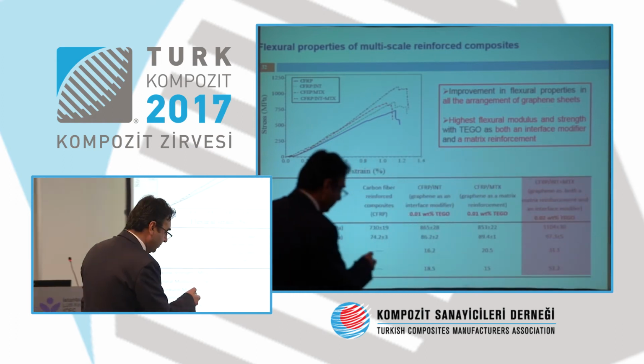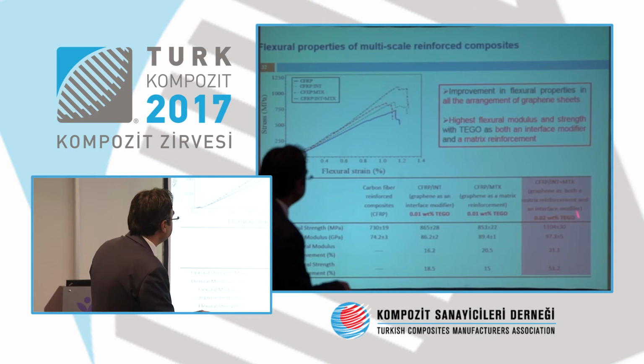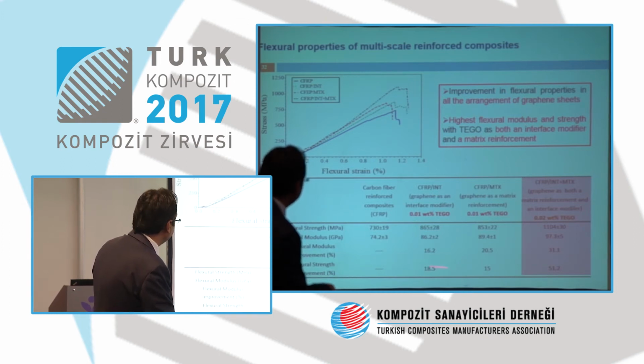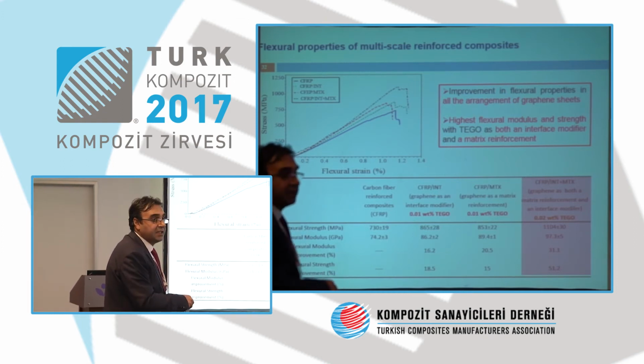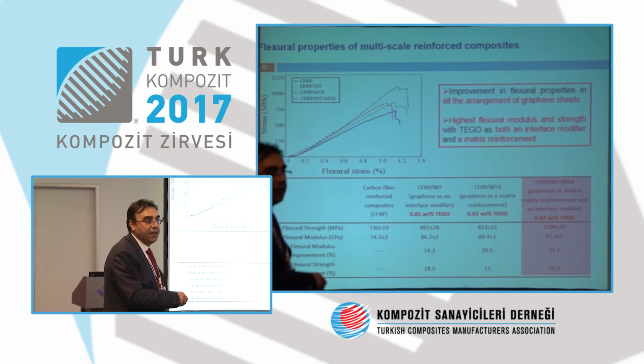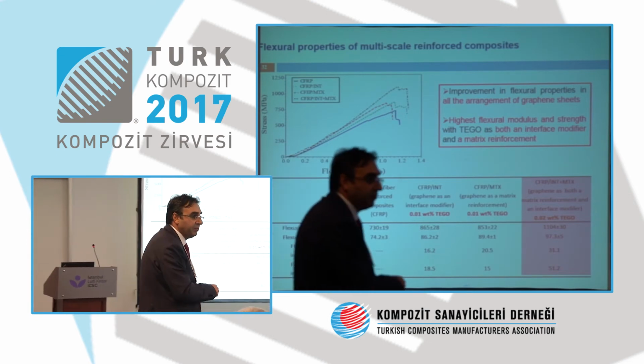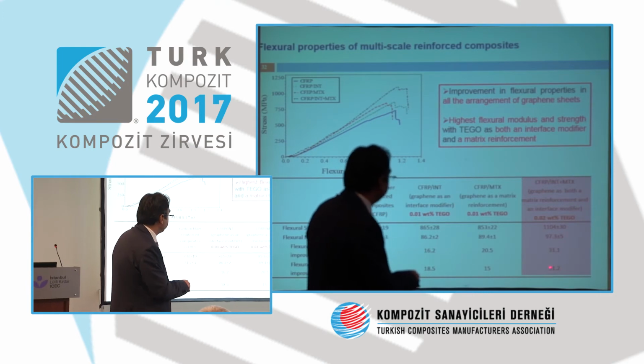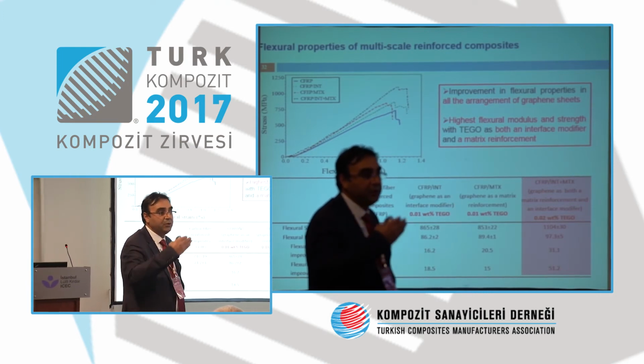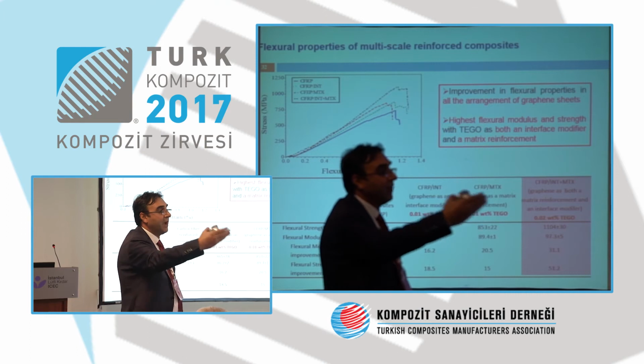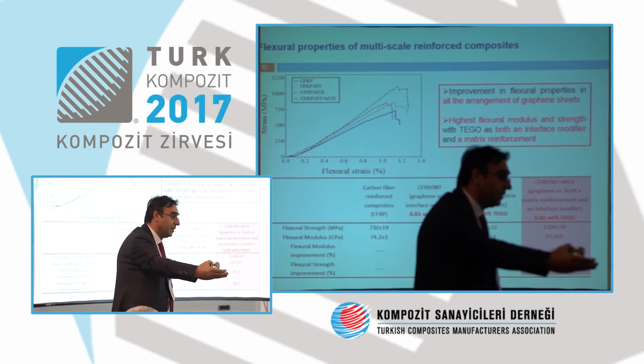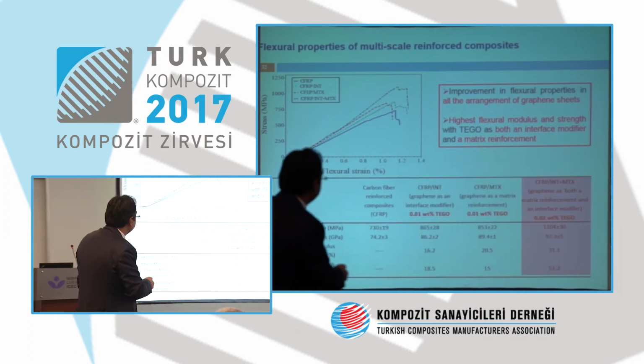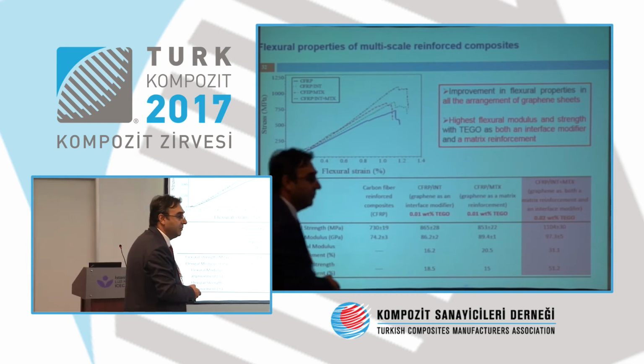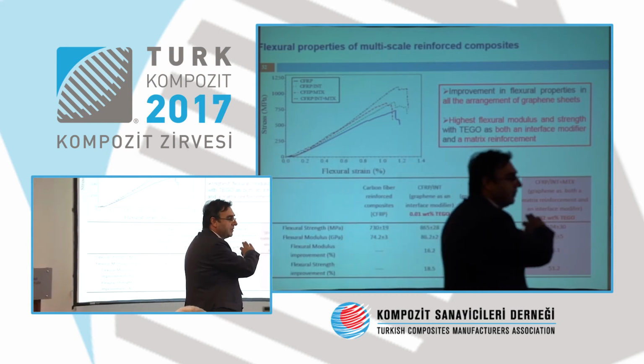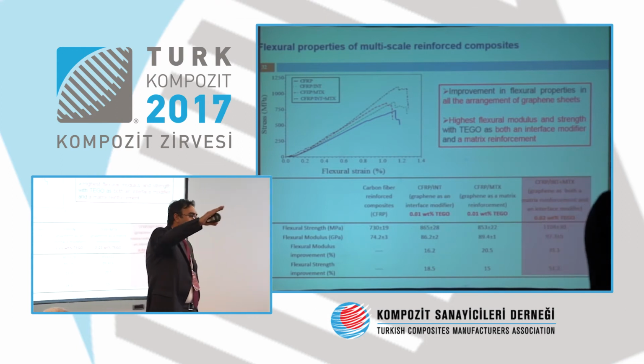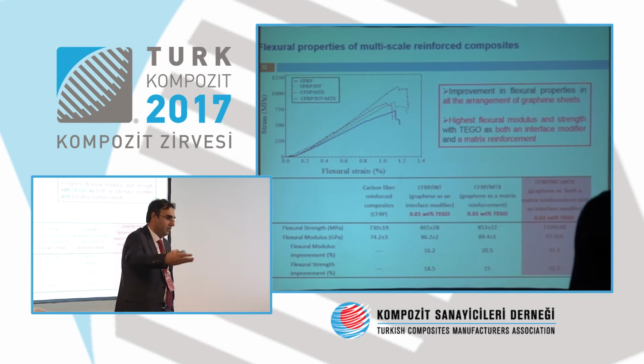And these are some of the improvements, and you see that for this hybrid system, the improvement is immense. This is far exceeding any data reported in the literature, considering the amount of material that we are adding. 52% is a huge improvement that we are getting without increasing the amount of carbon fiber reinforcement or increasing the lamination. For us, there was a percolation threshold. If you add above that, it is not going to bring you any advantage.